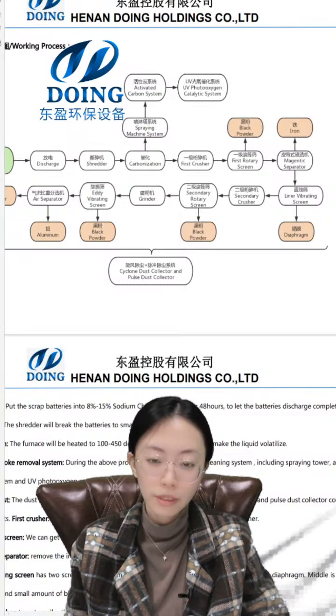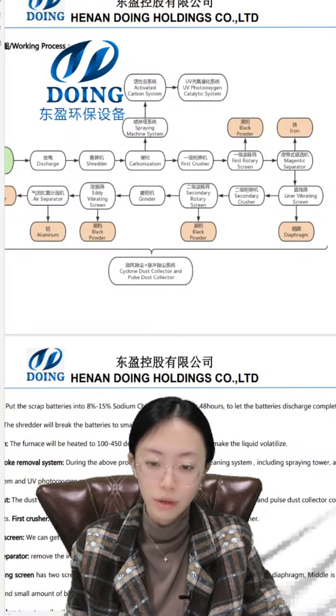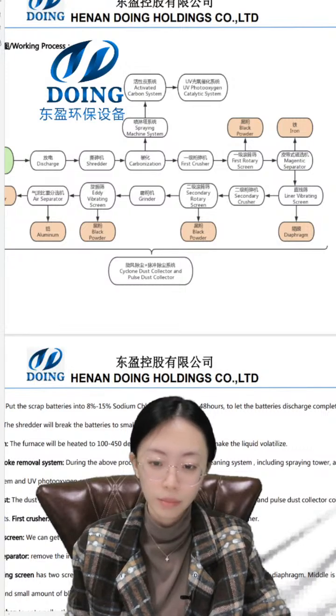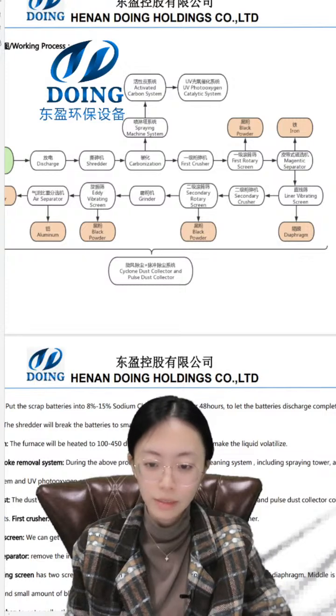Then there are two layers of screen mesh, one is 2 millimeter and the other is 100 mesh, stainless steel wire mesh, and the top layer of the screen is the diaphragm. We can collect 98% of the diaphragm in this step. And the second layer is copper, aluminium, and black powder. The bottom layer is the black powder. This is the 3 layers.